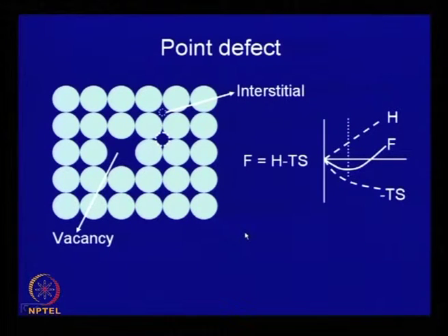Now, let us look at point defect. What is it? One of the common point defects is vacancy. A crystal is a periodic array of atoms, which is shown over here along this line, but often it so happens some of these atomic positions are not occupied by an atom, like here. This is a vacancy, this is a point defect, and sometimes we try to push another atom. It is possible when we do alloying: if an atom is very small, it can be accommodated within this interstitial space, the gap within the lattice, and if this atom is large, say something like here, it will try to push these atoms apart and cause a strain field.